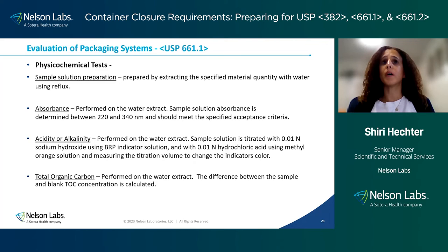And it is performed, it's this pretty simple absorbance test. We measure the sample solution, the water extract absorbance between 220 nanometers and 340 nanometers, and it should meet the acceptance criteria. If the absorbance is exceeding the acceptance criteria that is detailed in the chapter, it cannot be considered compliant. However, the cause for the high absorbance needs to be identified and quantified to see if it poses any risks to the end users, which are our patients.